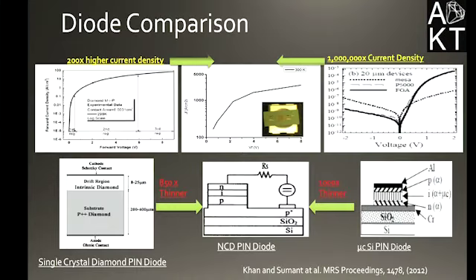So we looked at the material perspective, and we saw that there was this difference from a phase standpoint. But comparing an actually produced product, like a PIN diode, we had the ability to compare it not only to what's been done previously in diamond, but also the state-of-the-art in silicon technology. And we noticed some very, very interesting things. Not only were we able to produce much higher current density as compared to both silicon technology and the single crystal diamond, where as compared to the diamond world, single crystal diamond technology, we were able to produce over 200 times higher current density and over 1 million times higher current density than that of silicon. But we were able to accomplish this using much thinner layers of diamond. So now things like cost became mitigated.